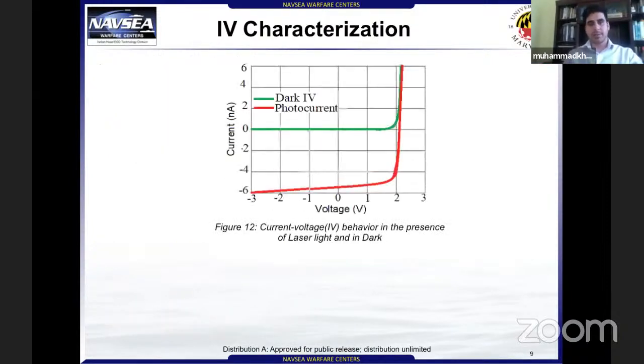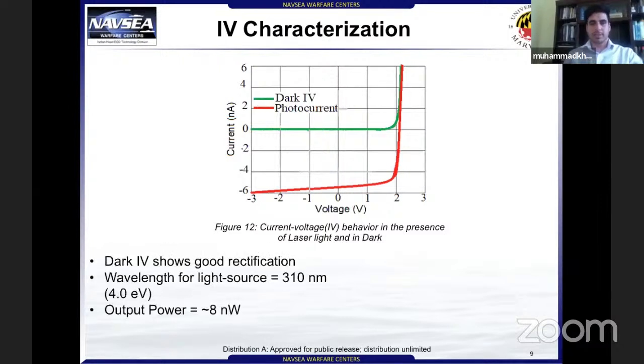First, we characterized the semiconductor junction itself. We did dark IV measurements, which means we tested our semiconductor junction without illuminating it with photons or betas. And we saw good diode behavior, good rectification, as shown in the green curve here. Then, since the working principle of a solar cell is similar to a betavoltaic device, we wanted to see if our device behaves as a solar cell. So we tested it under a light source, and we clearly saw a photo response as the IV curve dropped down to the fourth quadrant, indicating that power was generated. The wavelength of the light source was 310 nanometers, which equals about 4 eV. The output power was 8 nanowatts. To get output power, we simply multiply voltage times current, so we get 8.